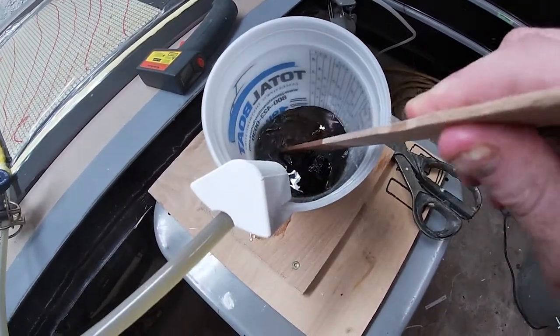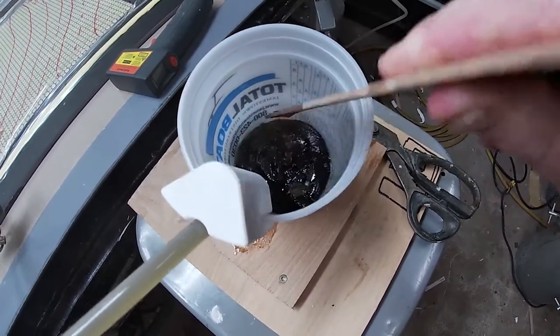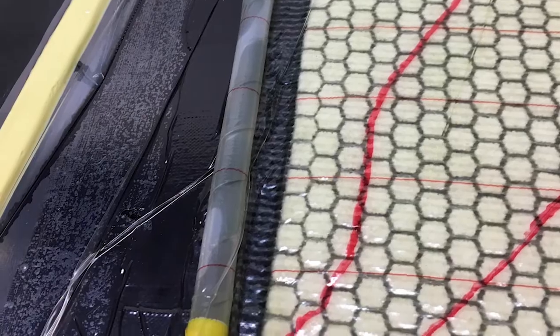Here's the gelled resin. You can see it actually gelled. This is about half an hour after it was mixed. And as it shrinks you can see what looks like air in that feed line.